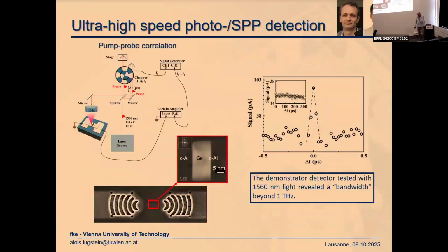I have shown you before that we can tune the length of this segment by this annealing process. And the idea was now, can we combine this ballistic transport with the decay of the plasmons? So we launch a plasmon, the plasmons propagate, decay at this interface, are injected into the germanium, and now they traverse through the germanium ballistically. That should finally lead to a really fast detector.